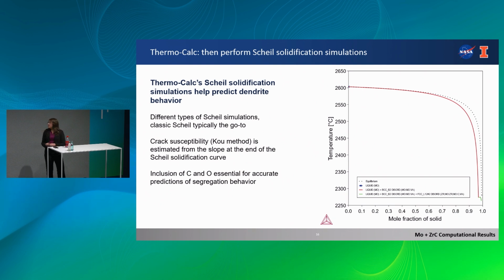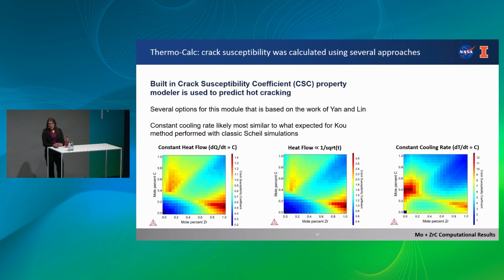Essentially, you base your crack susceptibility on the slope at the end of the Scheil solidification curve. So Thermo-Calc has a built-in crack susceptibility coefficient property modeler. This is essentially based off of the Scheil solidification curves. And basically the nice part about this is you can get this map of how your crack susceptibility changes with the amount of zirconium and carbon. And essentially, we're looking at the diagonal on these plots.